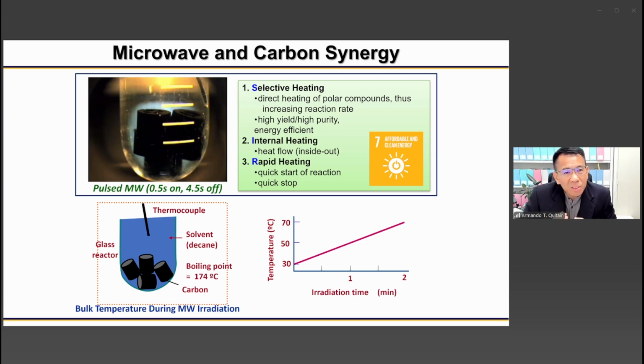And the moment you apply microwave, instantaneously you get those bubbles forming. And this bubble formation, we can actually interpret as the surface of the carbon reaching the boiling point of decane, which is 174 degrees centigrade, the moment you applied microwave on it. If you look at the bulk temperature, which is the temperature of decane, it only reaches about 70 degrees centigrade after 2 minutes.